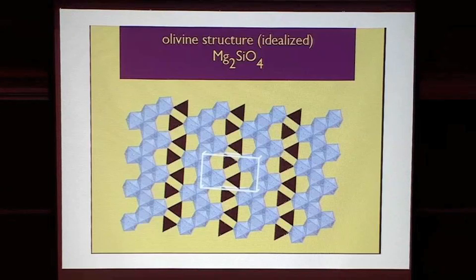A distorted hexagonal structure. In this case, you would have the silica tetrahedra pointing up and down. You would form a hexagonal structure if you go along the right direction for this one. And then what you would obtain is actually like a hexagonal lattice. I seem to recall that there are in fact high temperature hexagonal equivalents of olivine. Yeah, the potassium sulfate and potassium selenate. And it's been speculated that these could be stable in actual magnesium, in actual forsterite, but it's never been found. Isn't that right? Yeah.